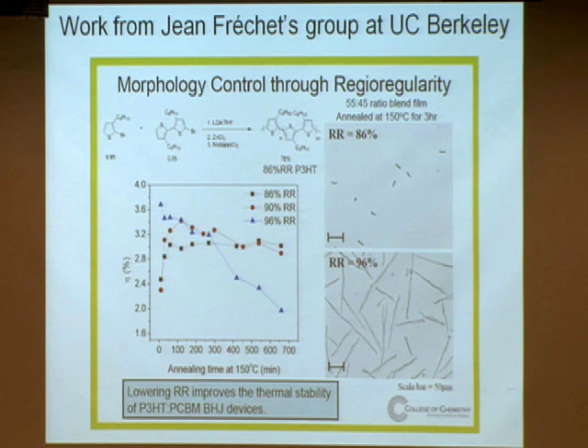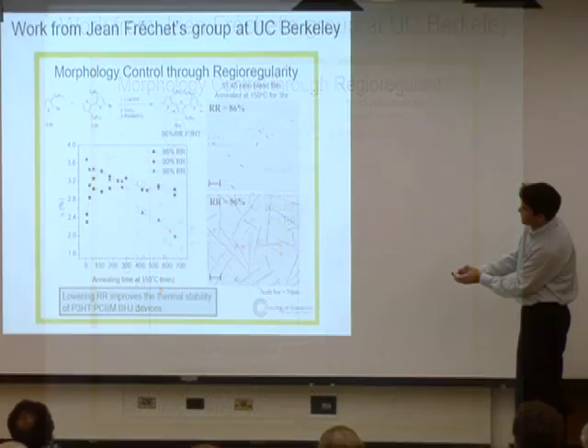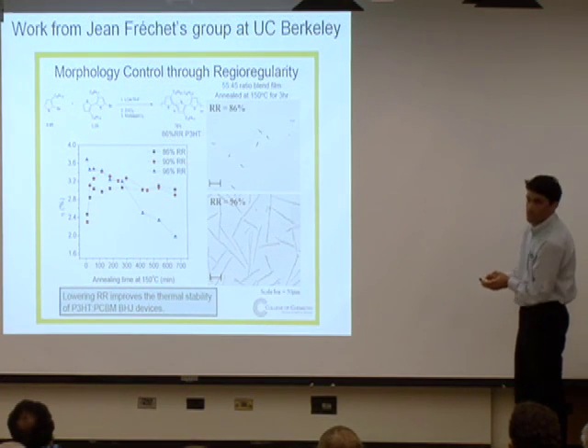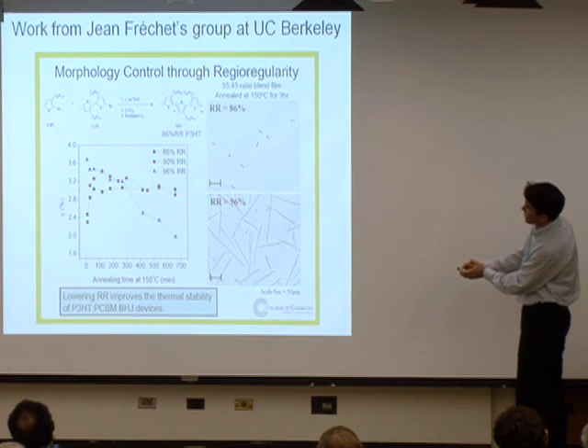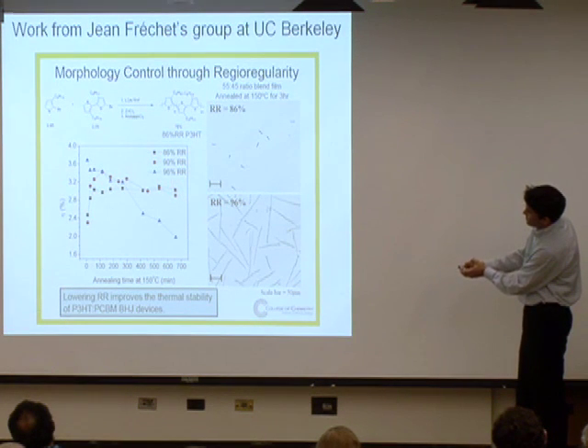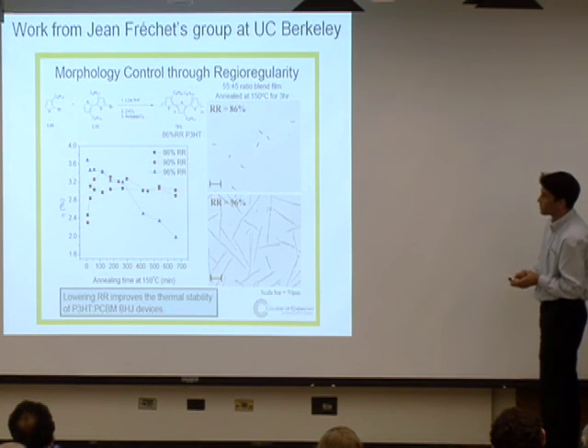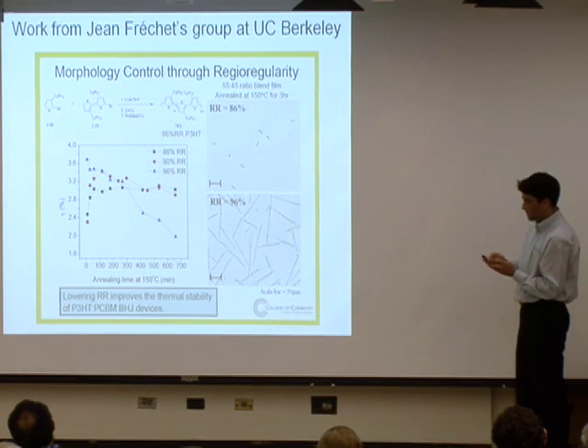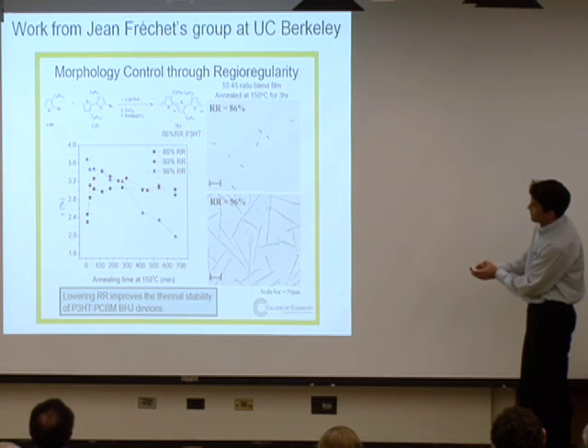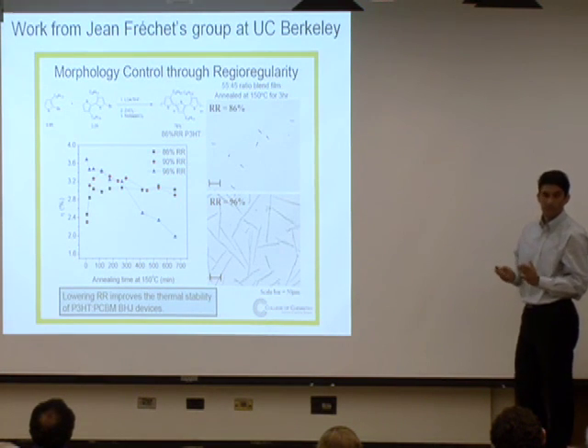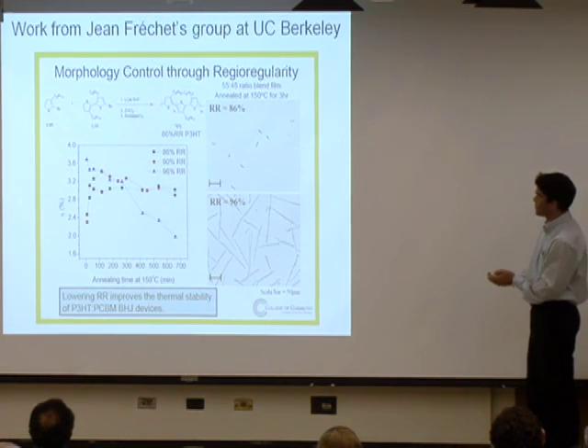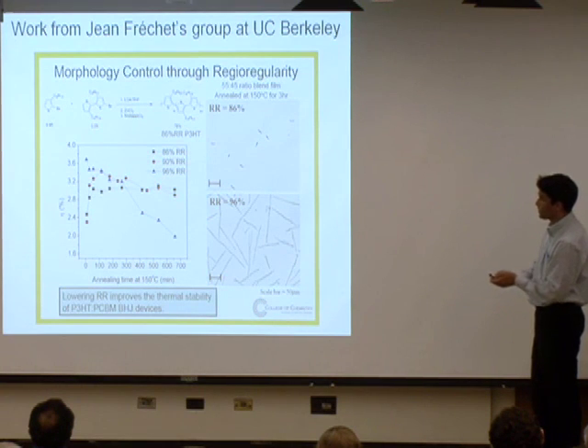And so it turns out that when you just deposit these materials at room temperature, the one that has the higher crystalline material is more efficient in the beginning, but as you heat it up, this is kind of like an accelerated aging study, you can see that in the end, the one with the least crystallinity is the one that provides the best performance. So in the past, it was thought that you need to have a really crystalline material in order to make a better device, but in Jean Frechet's lab, he showed that it's actually the opposite.